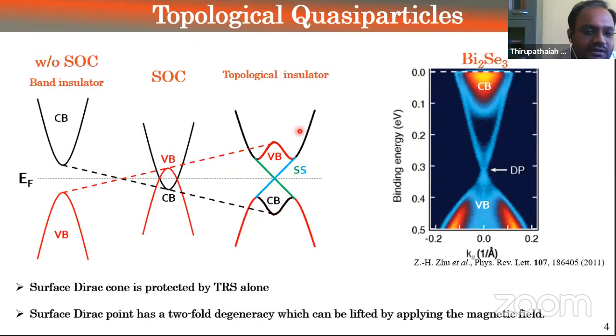So we all know these details, but let me start again from the basics, just to have some flow. We all know a band insulator has a big gap between the conduction band and the valence band. When you apply spin orbit coupling, in certain conditions they come together and there is an overlap between conduction and valence band. If there is no symmetry protection at these overlapping points, there will be hybridization, and they tend to open a gap. But surprisingly, now the valence band goes up and the conduction band comes down, which is a condition to develop topological surface states.